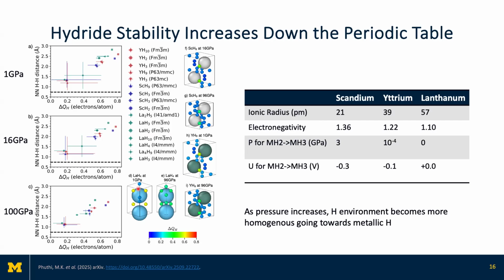There's a lot going on. Definitely, I see that point. But for simplicity here, we're interested in the thermodynamics of that convex hull in terms of which hydride is formed. Now, in reality, when I say there's YH3, it is actually YH3 minus delta. There are vacancies; you haven't filled up all the YH3 sites. Maybe not all of them will be filled up. It's YH2, but maybe it's YH1.98, right?